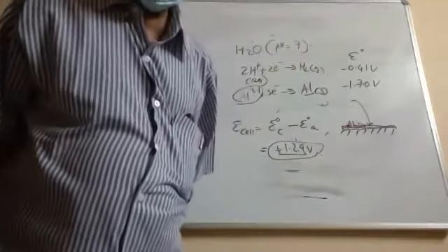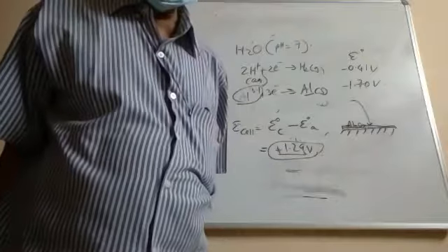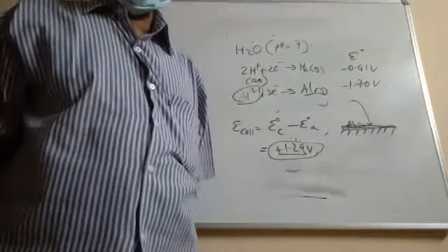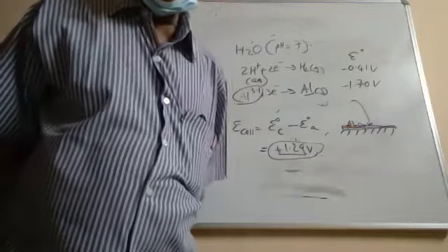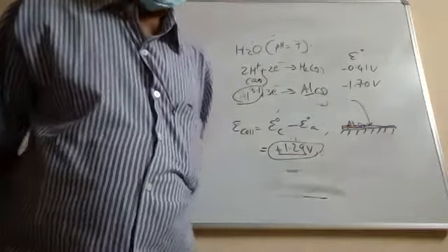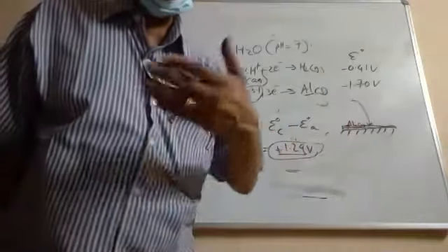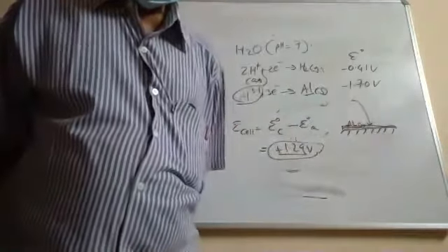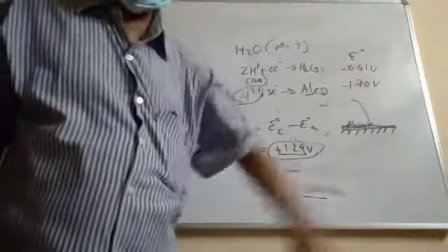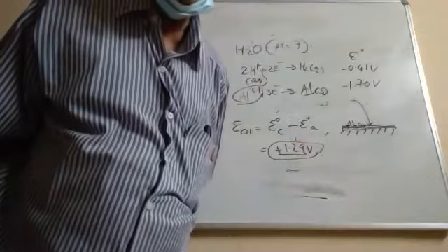If I have nano-sized aluminum powder, that is going to violently react with water. However, if I have a sheet of aluminum or a foil of aluminum or a container of aluminum, it's not going to show that violent activity because of the formation of what we call passive films. This is what we call passivation of the surface. The surface gets passivated. No other reactions possible. Am I clear here, folks?